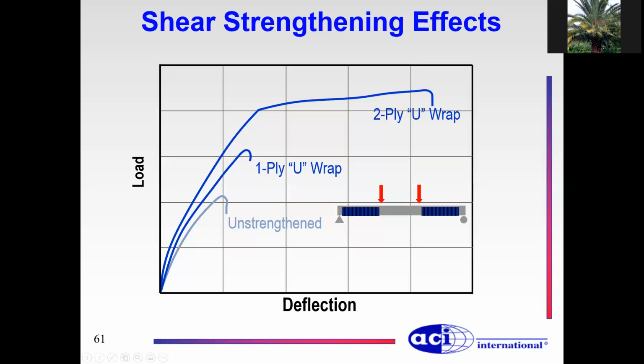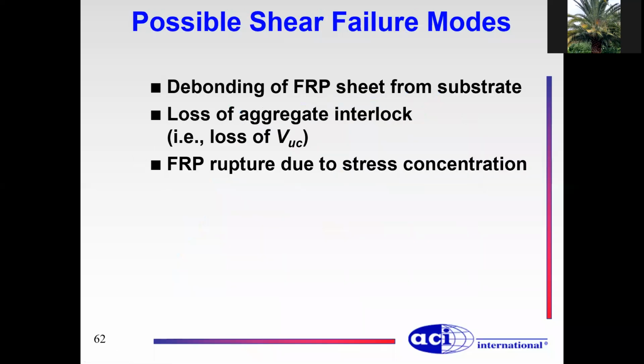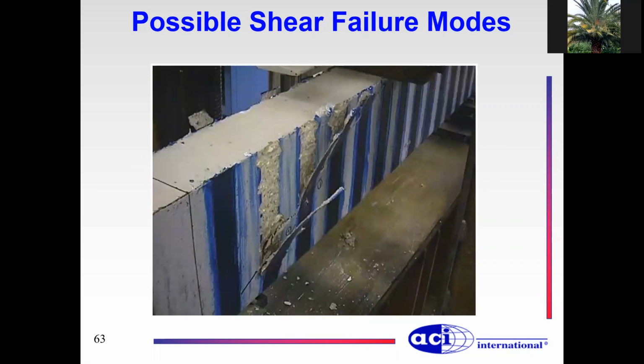So I have transformed the failure from shear failure to flexural failure, and that is the desired form of failure. Possible shear failure modes: debonding of the FRP sheet, loss of aggregate interlock, particularly if the cracks have become big, and sometimes you get FRP rupture due to stress concentrations. Typically, that's what it looks like.